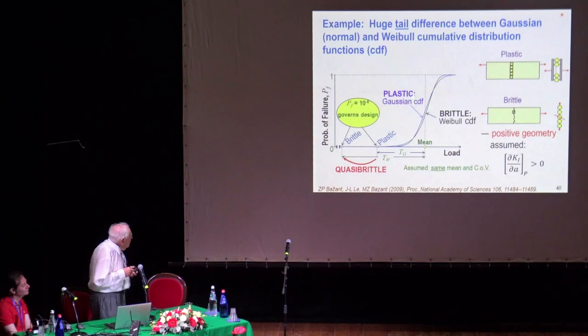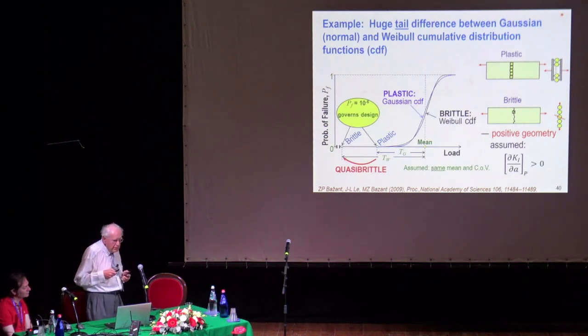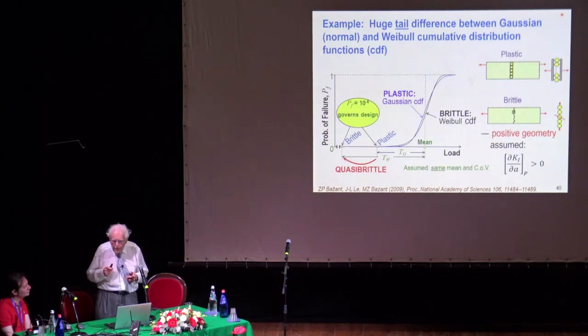Now, in failure, we have so far two models only. The weakest link model, brittle failure, that leads to the Weibull distribution, and ductile failure, which is called the fibre bundle model of Daniels, and that gives a Gaussian or normal distribution. They are indistinguishable if you do fewer than about 1,000 tests, because the histograms are always scattered. You cannot tell. You have to assume. However, if you extend it to 10 to the minus 6, the plastic failure is here, and brittle failure is here. There's a difference of 100%, 2 to 1. So there's a major problem.